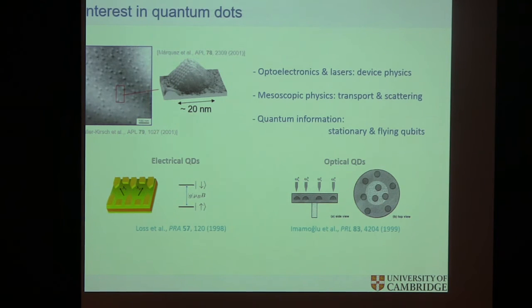At that point, you stop growing indium arsenide, and you say, let's continue with gallium arsenide again. And you cap the whole thing so that basically you have this layer, kind of looks like, feels like a delta doping of quantum dots. You have this fixed layer of randomly located islands, these quantum dots. They were first used for device physics.